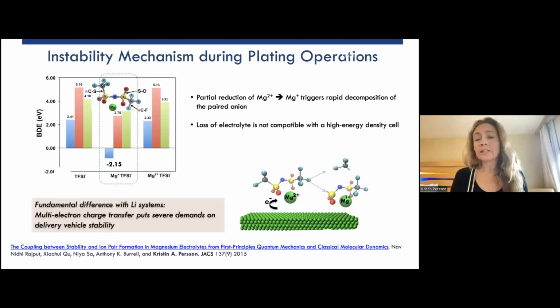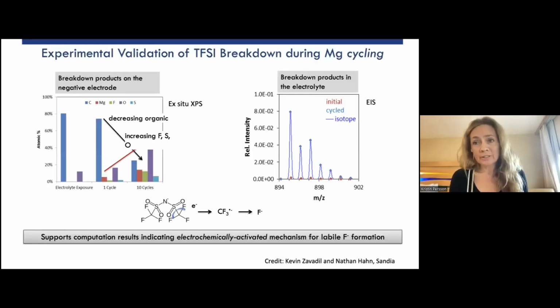And this is fundamentally a difference compared to lithium ion or sodium ion systems. All multivalent systems need to go through some sort of stages, very, very short lived, but still, of these intermediate charge states. This multi-electron charge transfer can, in some cases, when these intermediate charges are very unstable, put a tremendous chemical or electrochemical pressure on the delivery vehicle. So in this case, TFSI breaks. So of course, this is the computations.